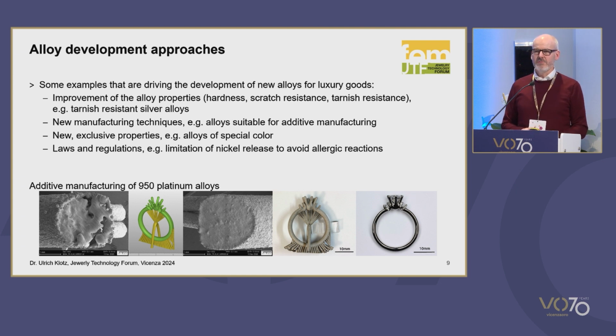So first of all, why do we want to do alloy development? We want to improve the properties like hardness, scratch resistance. Many years ago, nickel was replaced by nickel-free white gold alloys. We know about tarnish-resistant silver alloys or red gold alloys with high color stability. And in general, we want to improve the whiteness of the white gold, the hardness of the alloys. So there are many features that we want to improve with the alloys. And we also have new manufacturing techniques like additive manufacturing. The alloys that we know might probably not fit perfectly to that process because they were developed for cast and wrought alloys, so not necessarily are they fitting also to additive manufacturing.